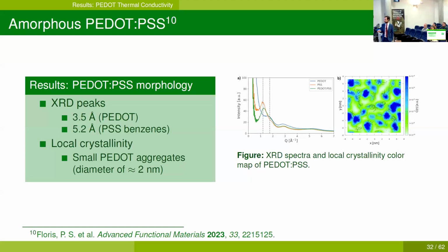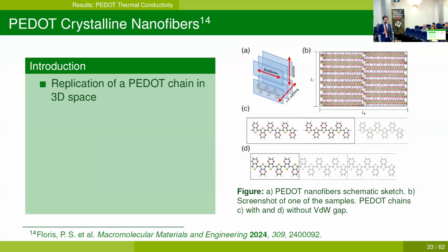And we have also used the local crystallinity custom measurement, where we can see that there are small PEDOT aggregates. You see the blue spots mostly. That's where the PEDOT chains are, approximately of diameter of 2 nanometers. We have also studied a different arrangement of PEDOT, which we call PEDOT crystalline nanofibers. We have followed a very different protocol to generate these samples.